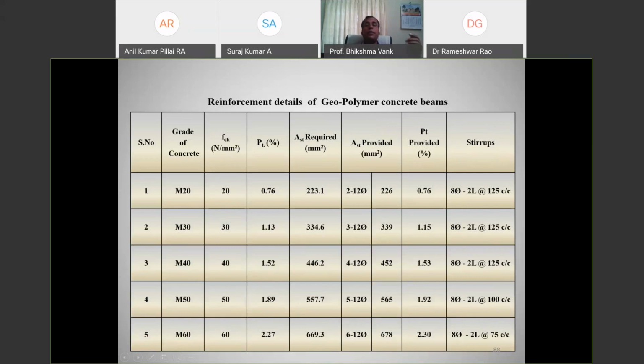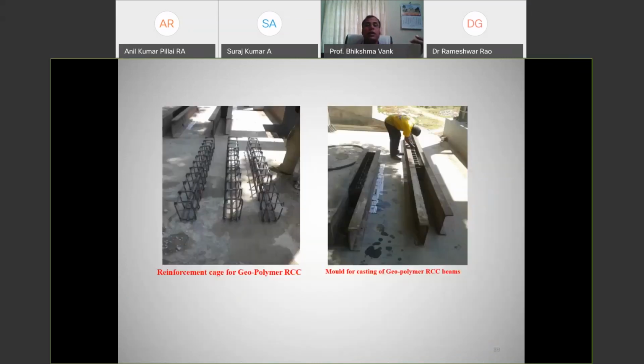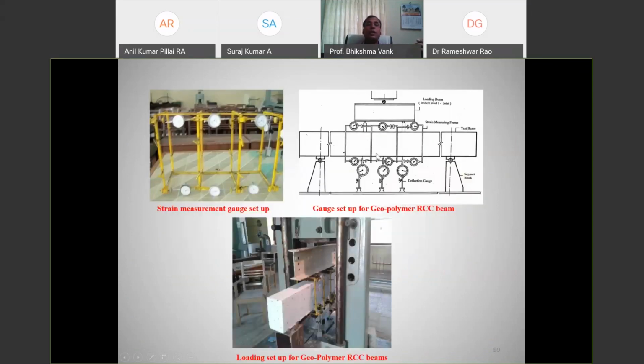Your experimental moment should be more than the theoretical moment. Then only your geopolymer concrete holds good. And in our case, we got all moments more than the theoretical moments. This is how the beams have been cast and tested under a universal testing machine, by comparing curvatures at the top and bottom.